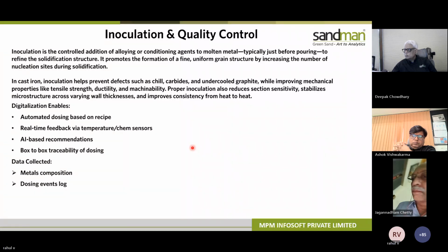and machinability. Proper inoculation also reduces section sensitivity, which I mentioned earlier, where the temperature profile has to be quite good along with proper inoculation. This way, we don't fall into defects like carbides in the thin section. Basically, we try to make a similar graphite structure throughout the casting. Proper inoculation stabilizes microstructure across varying wall thickness, and improves consistency from heat to heat, as well as box to box.